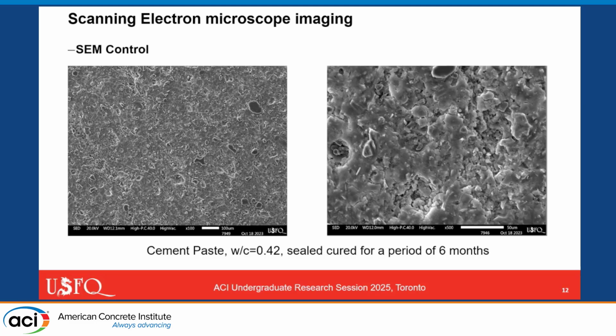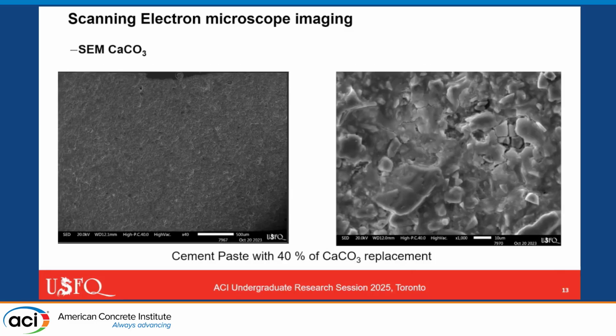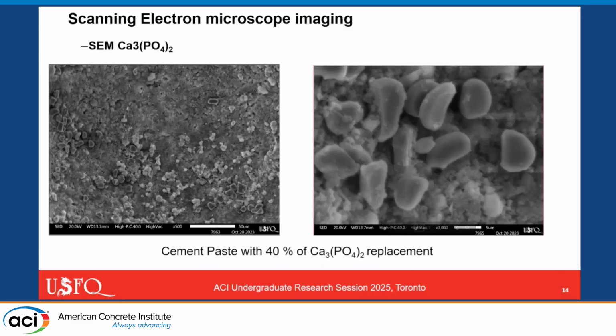In the scanning electron microscope imaging, in the control sample, we can observe what we already know about the cement paste matrix. So we can see the cement paste, we can see non-hydrated particles, the CH and CSH. And this one is with 40% of calcium carbonate, and what we observe is a little bit more densified. But what is really interesting for us is this one that has tricalcium phosphate.